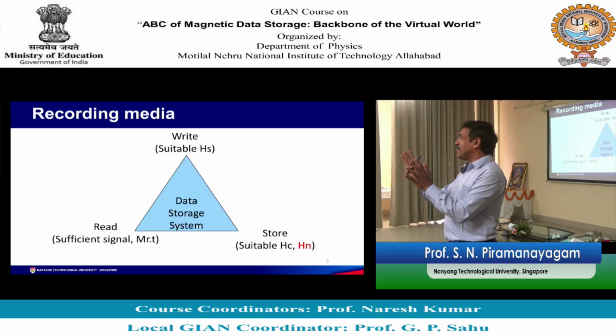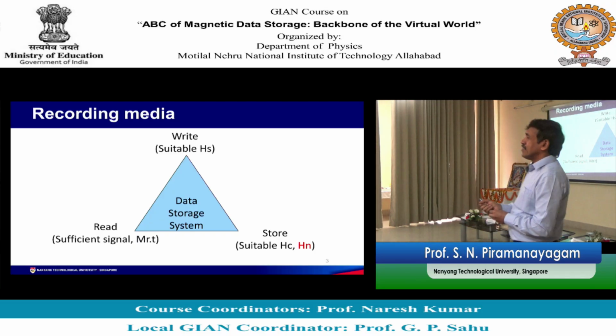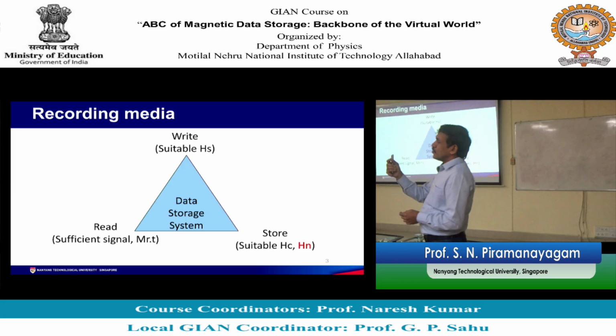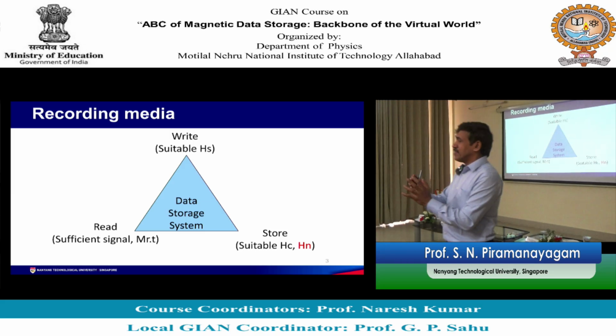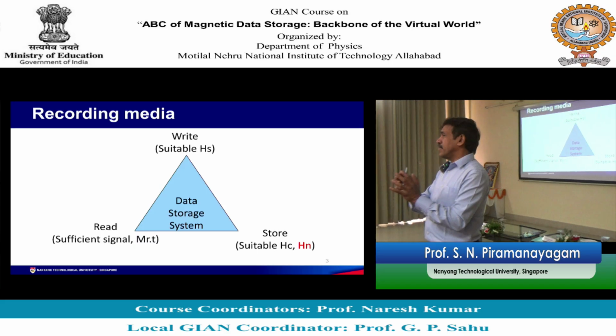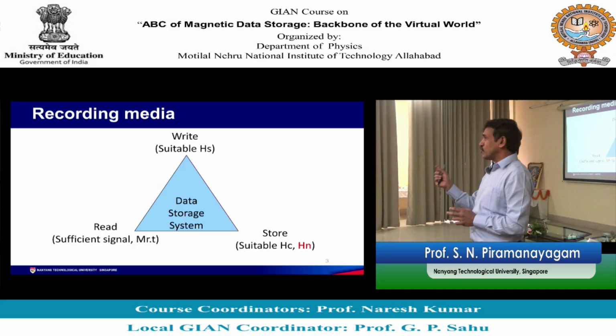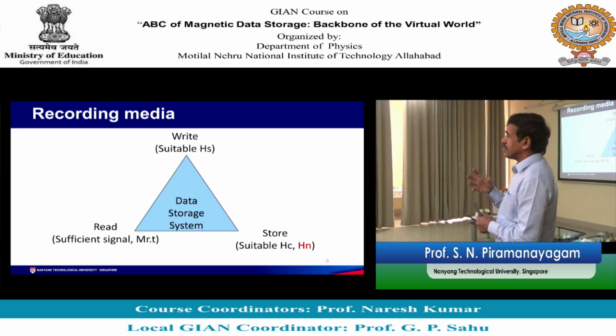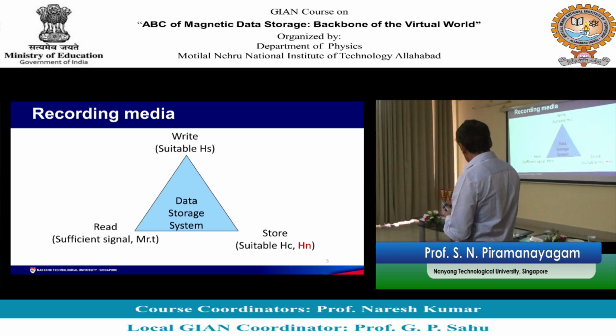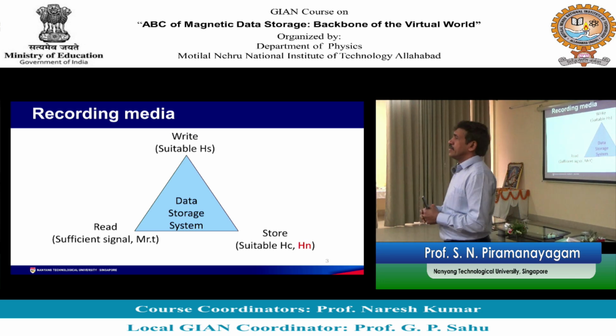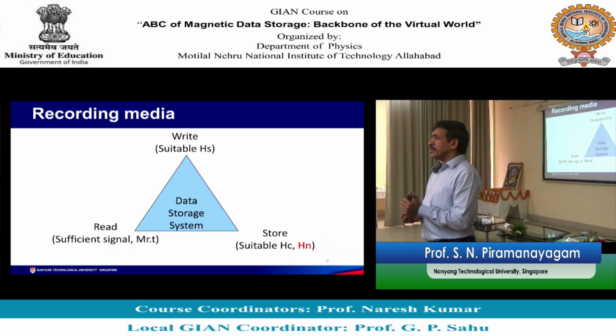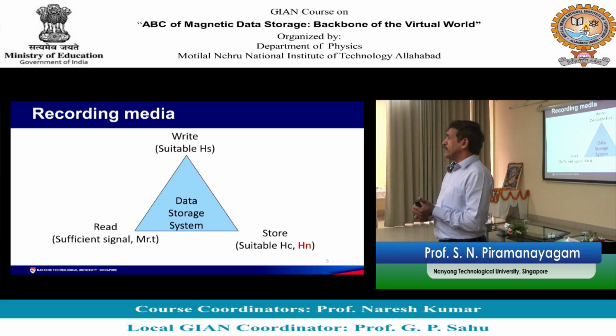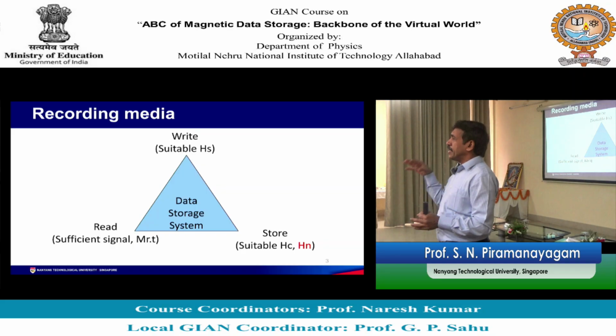Somewhere like 65-35. So you take iron and replace 35 atomic percent of iron with cobalt, then you have the highest saturation magnetization. That material has a saturation magnetization of 2.4 Tesla, so the maximum field that you can produce without spending more energy is 2.4 Tesla.